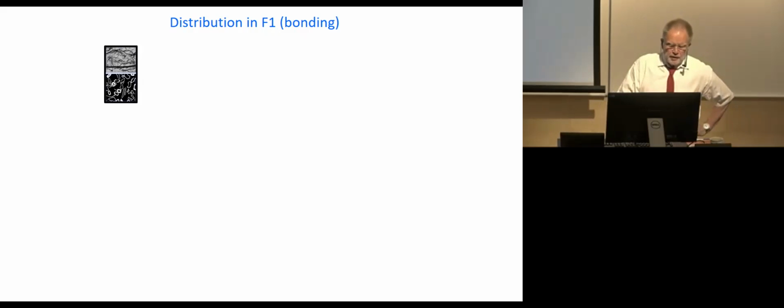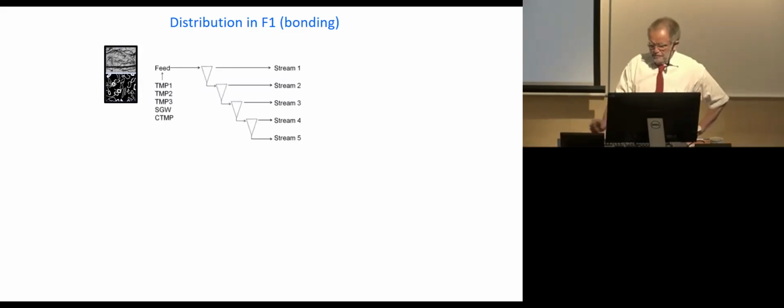So, referring to this, we try to develop a method to get the distribution in bonding of the particles to reflect their heterogeneity. So we took many pulps from different sources, different grades. We separated in hydrocyclones to get streams with different bonding level.